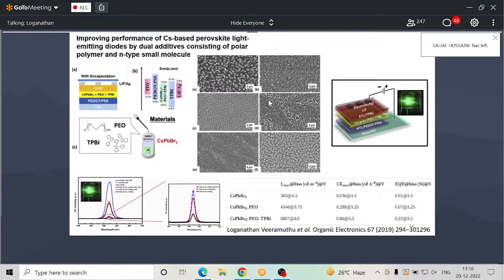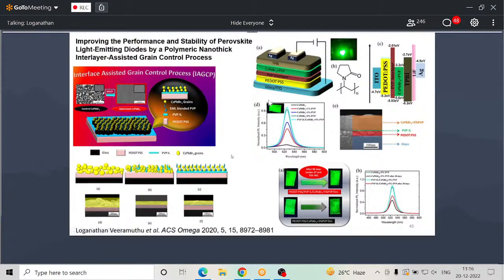In the previous case, you can see this is pure perovskite. In this, the perovskite has a very rough morphology. If you want to tune them and make very fine grains, then you will be getting very good efficiency. In this term, you can see in the pure case, the luminescence, the light output, is not that good, less than 400. But if you tune your system by using these kinds of small molecules and polymers, then you can enhance your efficiency.